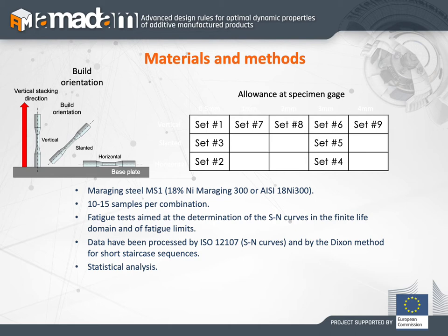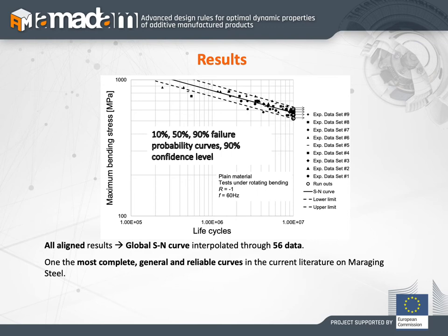And the results are collected here in this S-N curve. We have 56 data, which are probably the largest number of data collected for this kind of material in the fatigue curve. And we can state that no effect arose for the different combinations of allowance and build direction.